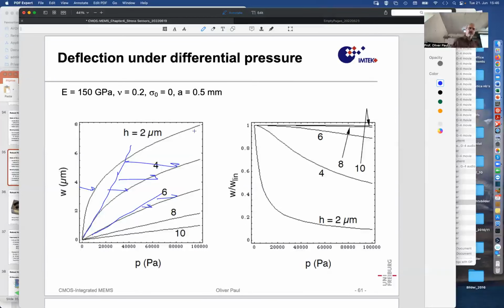And where do these nonlinearities come from? Why does this deflection of a membrane under pressure not just continue like that, but somehow become slower and slower? It gets harder and harder to deflect more because it bulges out of the plane, and then its length changes. It gets under some in-plane pre-strain, which would like to, or pre-stress would like to bring it back to the central position. And the stronger it is deflected, the harder this pre-stress or this in-plane stress would like to pull it back. So you're not only working against the bending. The bending stiffness alone makes this linear response. But the fact that you have at the same time an elongation stress that develops the stronger you are deflecting, that contributes to cubic power.